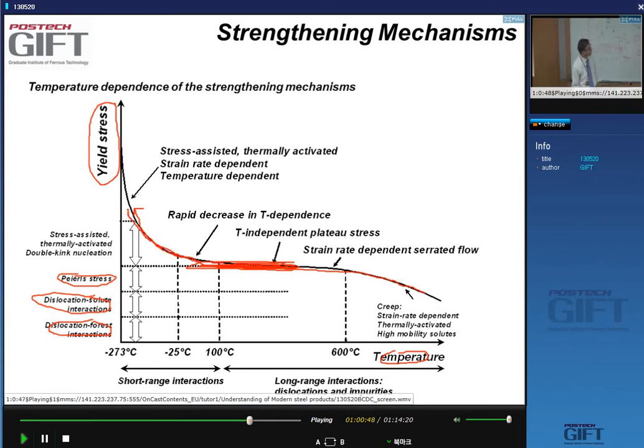This increase here is related, as you know, to the double kink nucleation becoming harder, because the double kink nucleation is thermally activated. That's why we get an increase here. This plateau is temperature independent, though we say there is a slight temperature dependence which comes from the temperature dependence of the elastic modulus properties, like the shear modulus and the Young's modulus, so there is a little downward slope.